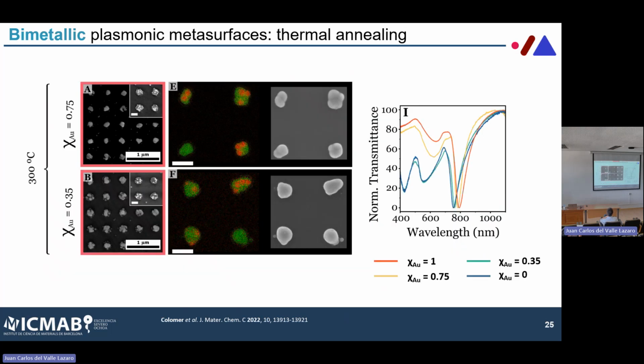But the real thing that motivated our study was to try to create a bimetallic system. At certain conditions, specifically at 300 degrees, we were actually able to put together both gold and silver and create particles that show patchy elemental composition. So you're not alloying the system completely, but you still maintain a gold enriched area and a silver enriched area, which depends, of course, on the initial composition.